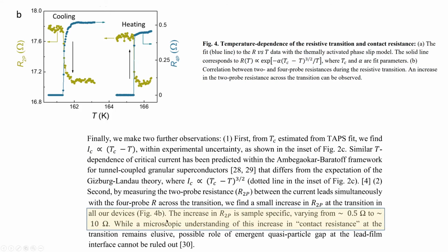but the other thing to note is how pervasive this signature is. It's clear that it was produced in many samples, many different devices, and although the range of this effect is basically varying from one device to another, in some places it was as large as 10 ohms. So this is then basically interpreted as a contact resistance, and that is somehow happening exactly at the same time as the